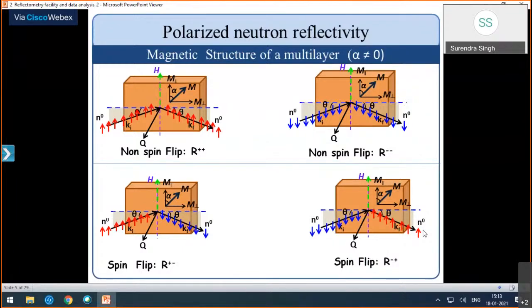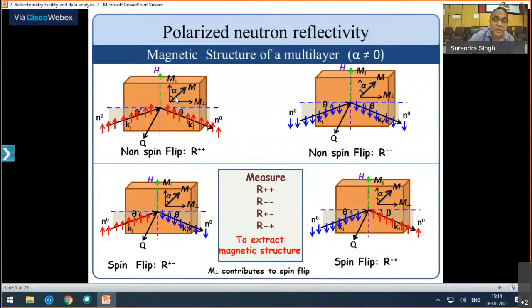Plus plus R, minus minus R, plus minus R, minus plus R. We can get amplitude of magnetization, which gives the structure of the magnetic structure, a layer magnetic structure. As I said, this spin flip is coming due to the M perpendicular component, noted here, sine theta, M sine theta component.